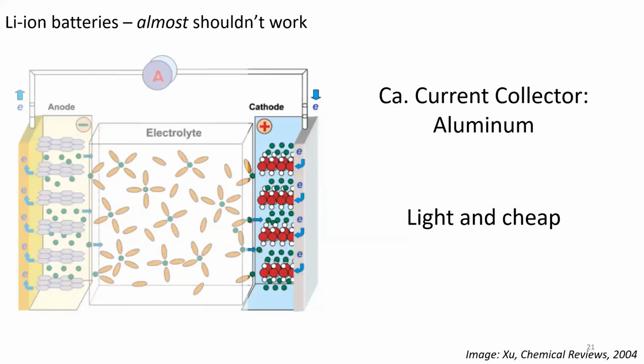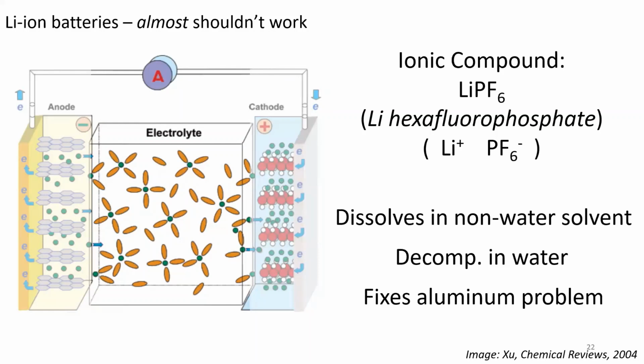Awesome. So let's look at the electrolyte in the middle. So the electrolyte has a solvent and then some ionic compound that's being dissolved, and that ionic compound has to involve lithium because that's what's getting moved back and forth. So what is exclusively used in commercial batteries so far is lithium hexafluorophosphate, LiPF6. So lithium has that positive charge, and then the PF6 has a negative charge. It's a fairly big anion, and then it has a bunch of fluorines on it that like having an extra electron around. So that makes it a fairly stable anion. That means it will dissolve into our organic solvents. So we're not using water in our commercial devices. Organic solvents usually aren't good at dissolving ionic compounds, but having a big anion like that helps.